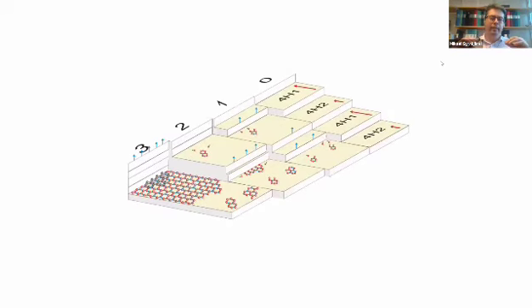The delicate thing here is that when silicon carbide is heated up, you have different steps. When you have the silicon and carbon, you have bilayers, and you stack them in different ways. Then you have different surfaces, and there can be step bunching as small steps. This creates a problem in the growth, but this is also the way to make the graphene on silicon carbide, because it starts to grow from one edge and so on. This surface reconstruction of silicon carbide is very important, because when you heat it up, you start to have a surface reconstruction, and then the atoms start to leave, and you have the graphene and so on. I will come back to this surface reconstruction idea in another application.